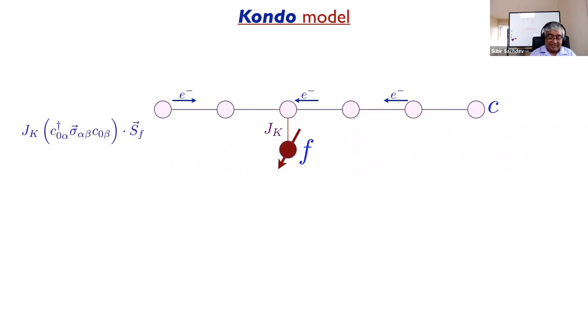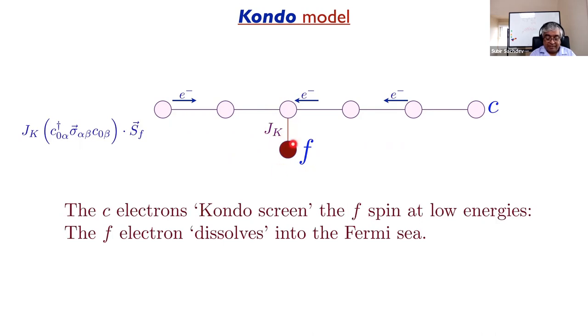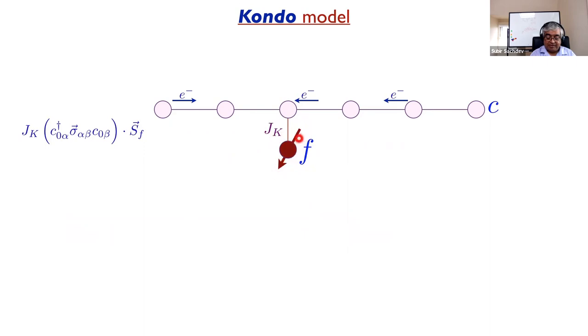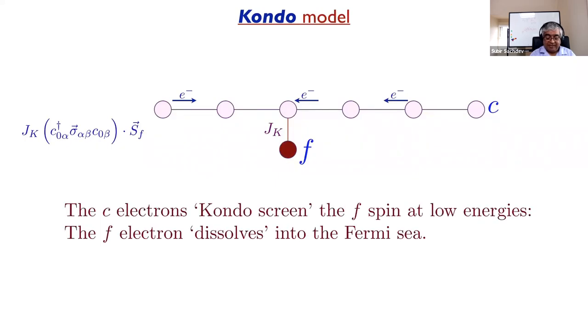What we learned in the 60s and later was that this Kondo coupling is always relevant. That is, if you go to low enough temperatures, this coupling effectively becomes infinite. What that means is that at very high temperatures, there's an electron trapped here, and you would see a Curie susceptibility. It would behave like a free spin with a 1/T susceptibility. When you go to low temperatures, that moment disappears. This spin dissolves into the Fermi sea. It just gets screened by the other electrons and forms singlets with them over long range and basically disappears. So that's Kondo 101 in very simple language. And of course, there are huge amounts of theory, and the RG was developed to understand this problem.